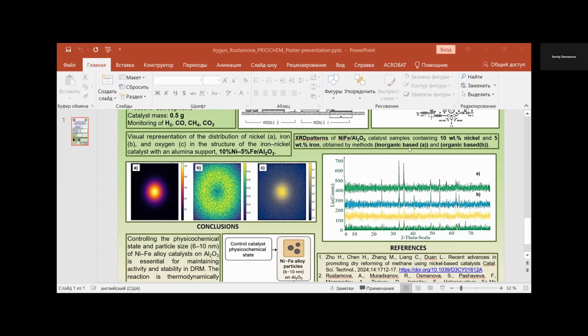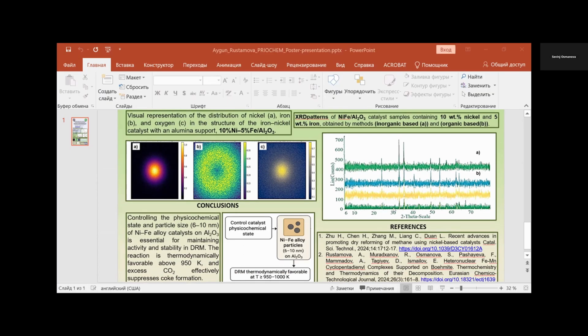are two methods, inorganic based and organic based. In the inorganic based one, you can see the higher peaks, which means a higher crystalline structure and larger crystalline size, while in the organic based one, there are wider and broader peaks, which shows the smaller crystalline size.